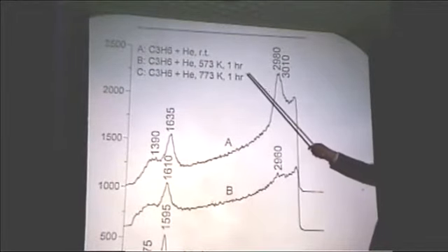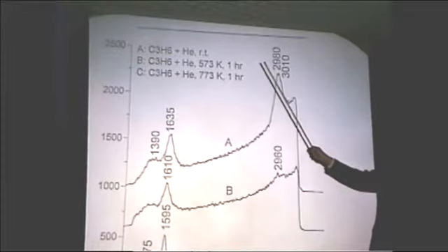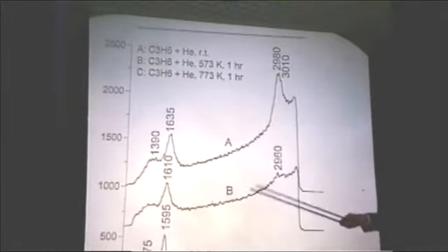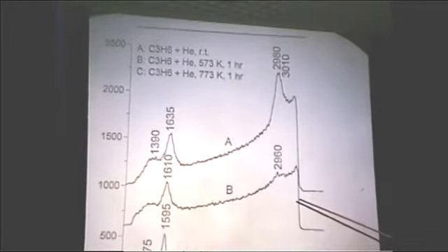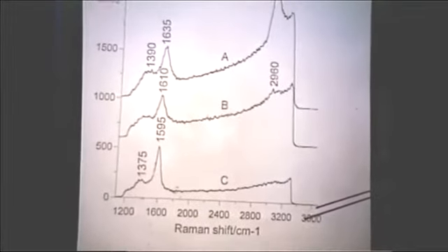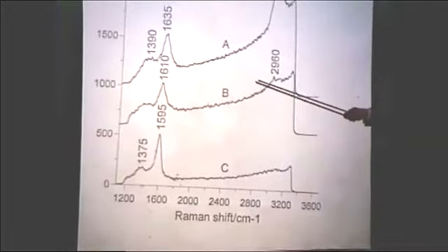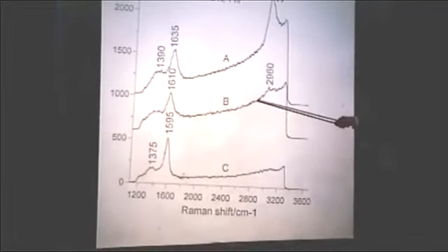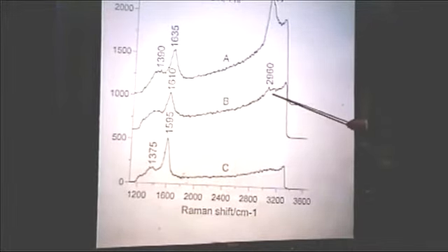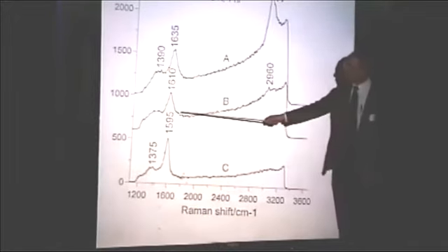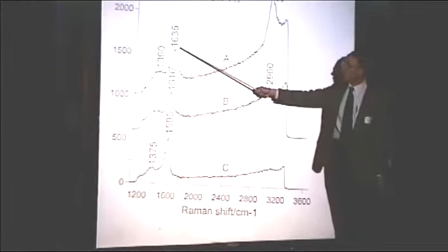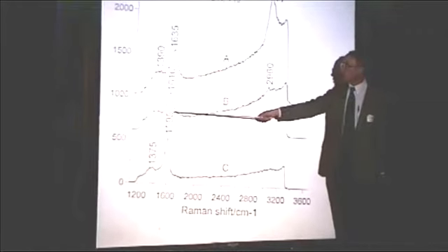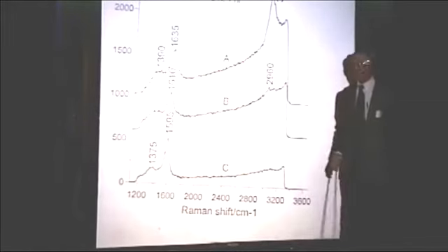So it's the same stuff at room temperature. But now, if we heat not at 500 degrees C, but only at 300 degrees C for 1 hour in propylene and helium, we have a vastly different spectrum from what we saw with the ZSM5. Remember, with the ZSM5 at 500 C for an hour, there was hardly any change in the spectrum at all. Here, we've lost most of the hydrogen. We've experienced a substantial shift in the position of this band in the CC stretch region, so that now we're in the polynuclear aromatic region already at 300 degrees C.